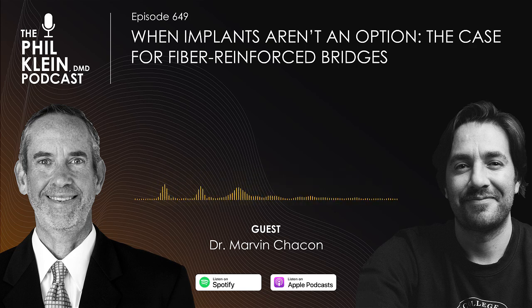That's a very good question. How do you deal with failure? One of the most frequent failures will be the debonding of the wing or fracture of the wings. And that is because the dentist doesn't respect the minimal depth of the preparation. That will be 2.5 millimeters. There is 1 millimeter for the fibers and 1.5 millimeters for the veneer material.